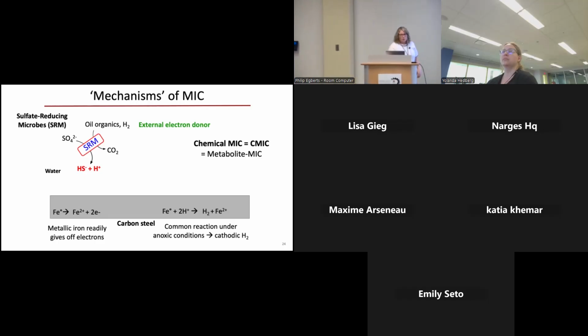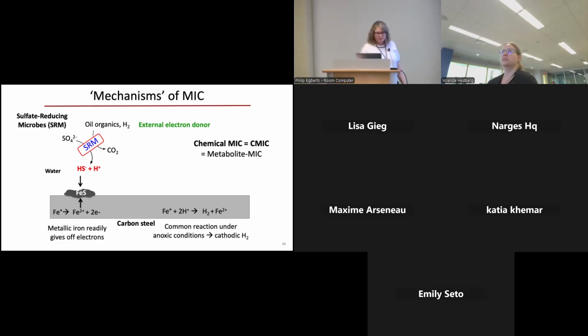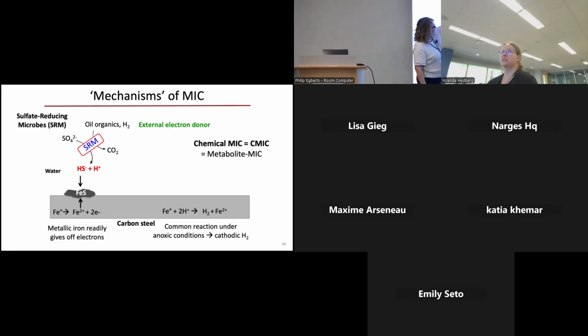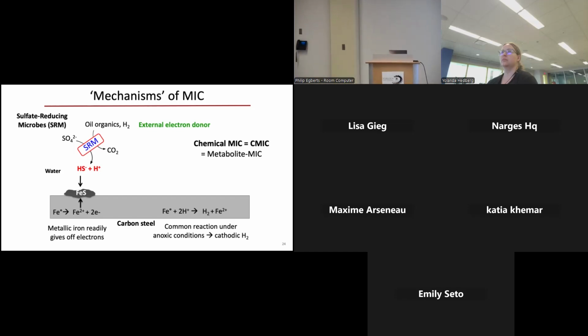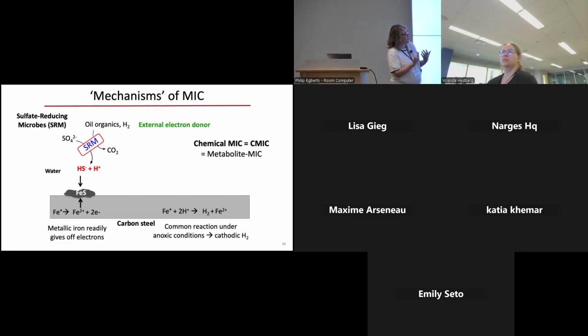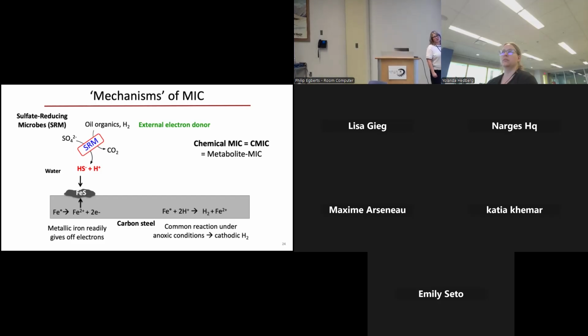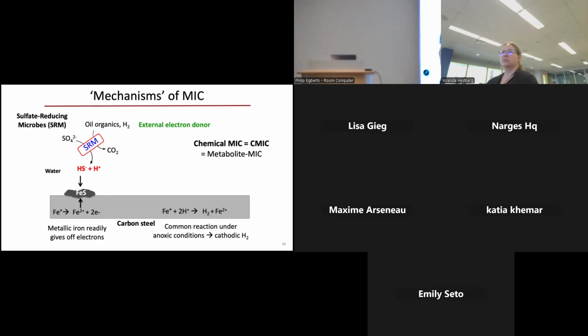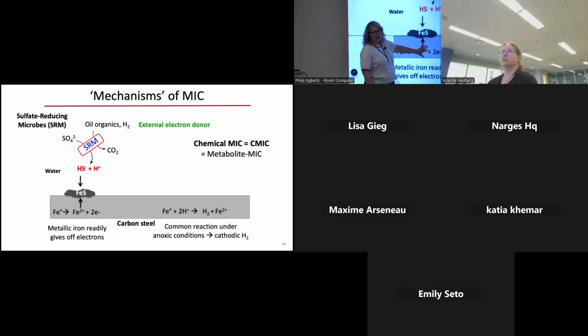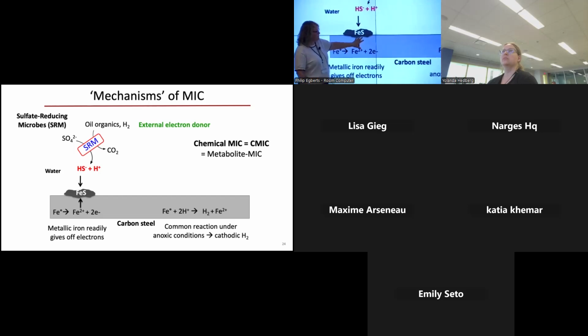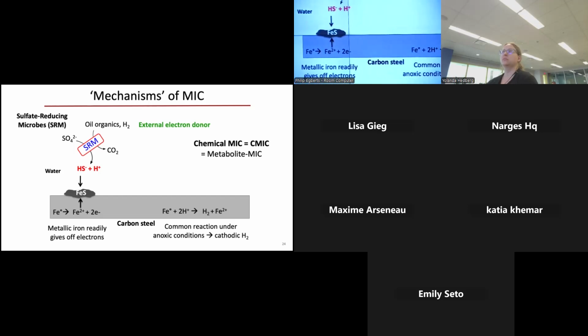What happens in this scenario is that hydrogen sulfide can chemically react with that iron 2 from the dissolution of metal to form iron sulfide. It's a black precipitate that can then form on the surface of that metal. This type of microbial corrosion we refer to as chemical MIC, or CMIC, also known as metabolite MIC. The reason it's called metabolite MIC is that the microorganism produces, through its metabolism, some metabolite or end product that can then chemically react with some component of that metal. So we have this external electron donor.